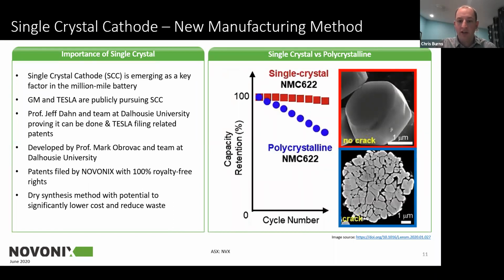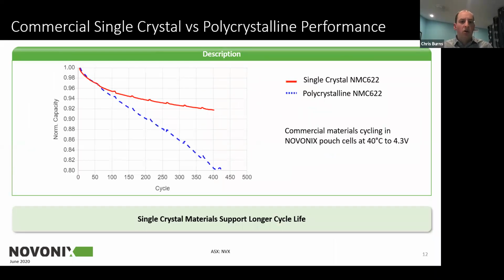So what's shown on the right here is an image from a paper that shows a cross section of a single crystal particle and a polycrystalline particle on the bottom. And you get cracking within the grain structure of the polycrystalline after extended cycling, as illustrated in the schematic. This can lead to capacity loss. But the single crystal material is very robust and resilient to this cracking over time, and that helps it achieve much longer cycle lives.